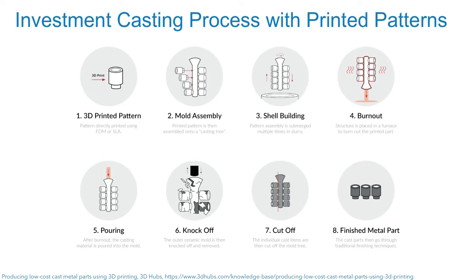You do that by repeatedly dipping it in a ceramic slurry and then backing that with a sand coat. So it's kind of a stucco process. You then melt out all the wax, flip the shell over, and pour in metal. So what you've basically done is transferred geometry, a surface impression, from wax to ceramic to metal. Then chop your metal parts off of the tree, heat treat them, machine them, and you have finished metal parts.